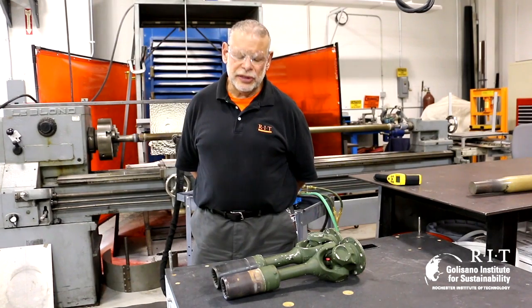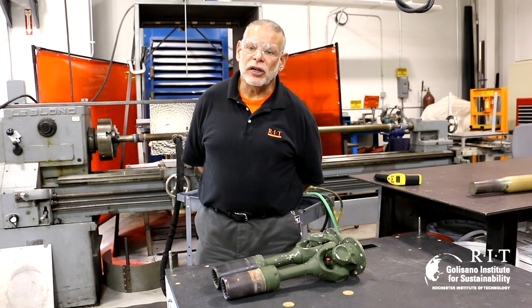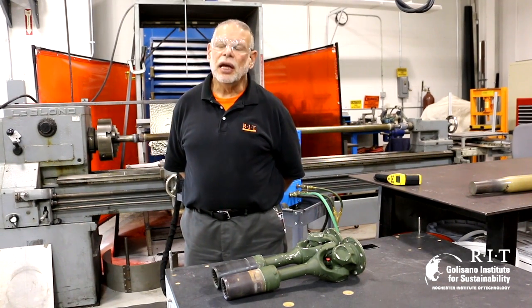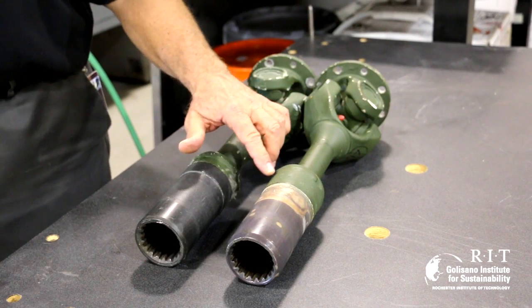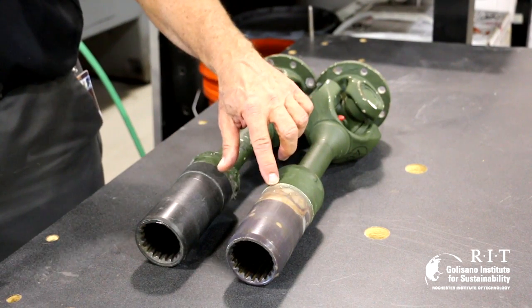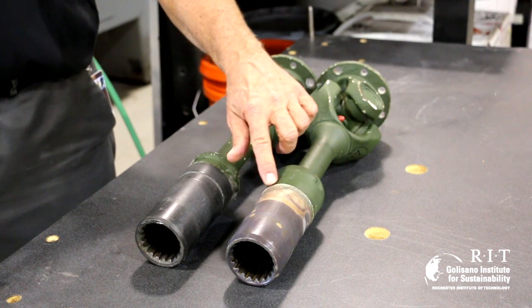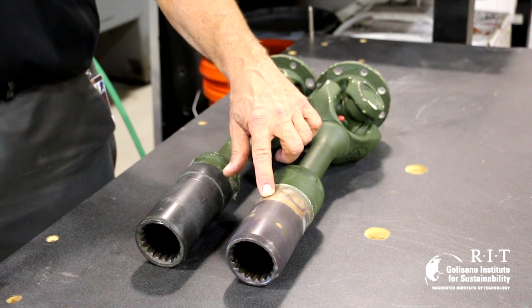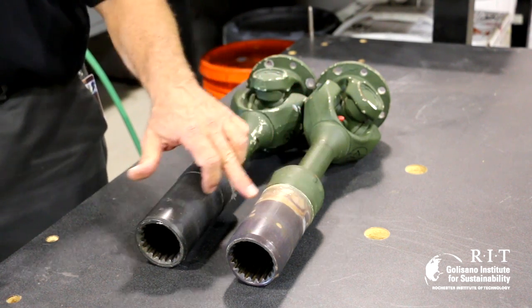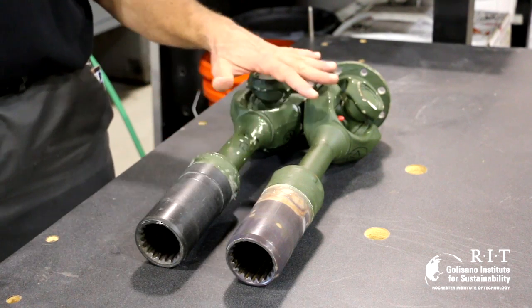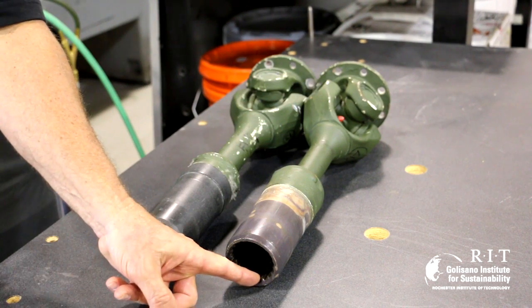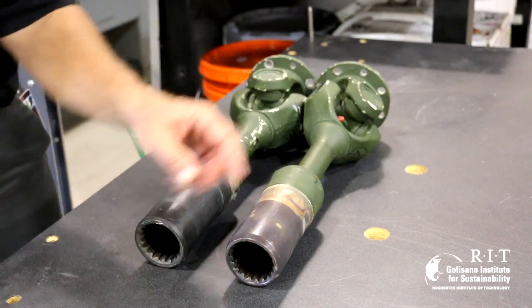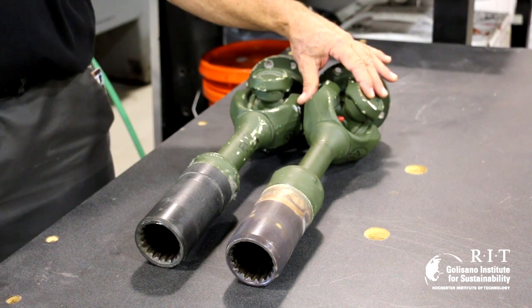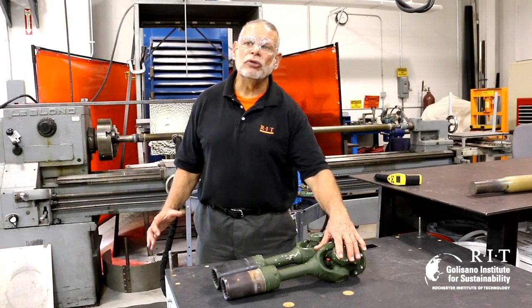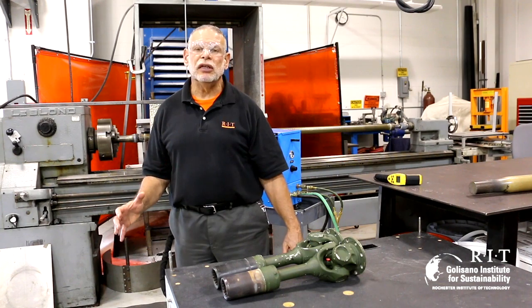As I mentioned previously, I found these components on a pile on the side in the factory, and they had failed because of the coating debonding from the step here. The debonded coating enabled water to get underneath it and cause corrosion. And I asked them if we could remanufacture them. And they said, yes, we could. However, we could not destroy the coating in the center or the U-joint on the back end.